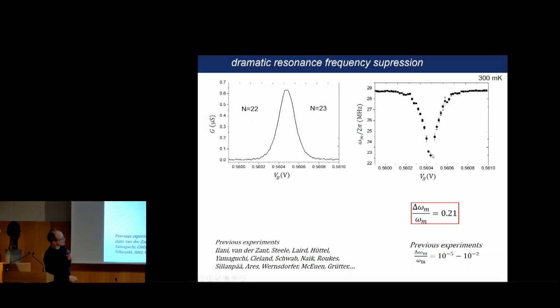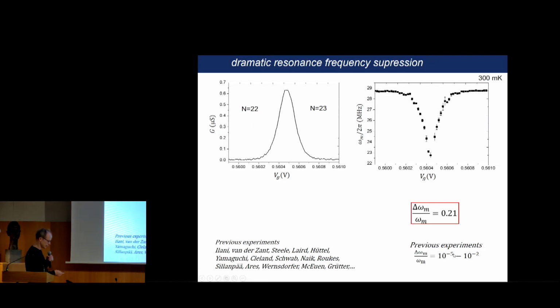what we observe is a dramatic reduction of the mechanical frequency. So when it's not coupled, when the effect of the coupling is cancelled, you have a frequency near 29 megahertz, and here we can go down to 22 megahertz because of this coupling. And so we have a 21% renormalization of the mechanical frequency, which is much larger than what has been achieved in the past.